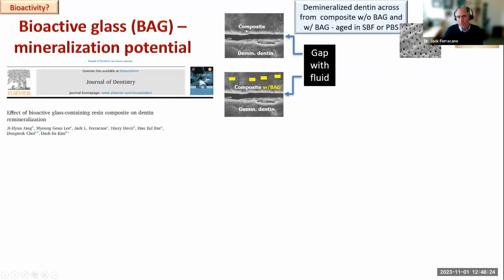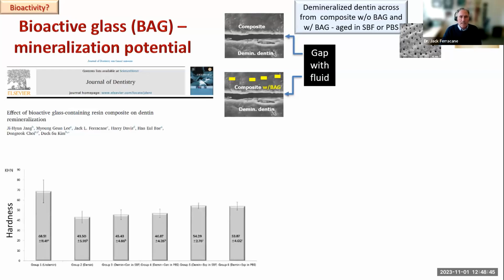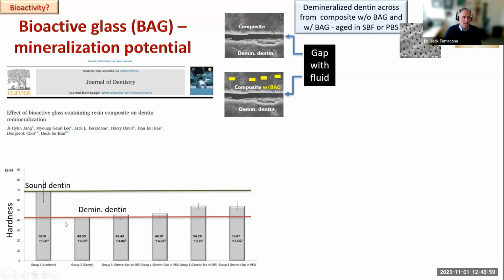In one case, the composite was just a traditional type of composite. In the second, the composite had bioactive glass particles in it, similar to the Hench formulation, but we make our own. And the gap was filled with fluid, which was either simulated body fluid or phosphate buffered saline. And this sat for about a week or two. And to start off, to determine what was happening, we measured the hardness. So they measured the hardness of sound dentin, and you see it's nearly 70. And then the hardness of this demineralized dentin is about 42, so about 30 units less.